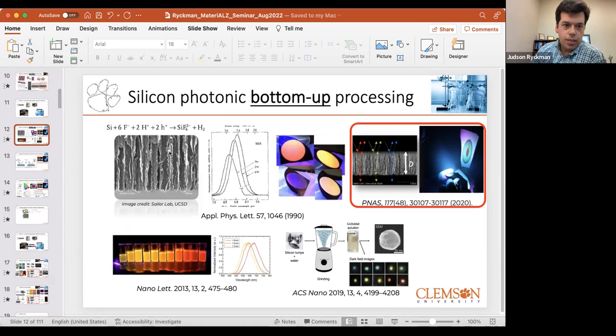My question is, how can I determine the number of pores and pore volume in a silicon porous film? Okay, yeah. So I guess there's a few different measurement techniques. You can do a standard SEM image, and then there's some distribution analysis you can do to see what is the average pore size. You can do cross-sectional imaging. There's also some more advanced techniques with gas adsorption analysis to get the average pore size and the specific surface area of the entire system. We also use gravimetry, where you actually measure the mass of the chip before and after porosifying it to see how much silicon you remove. So there's a few different techniques like that. I'll say in our case, the pores are disordered, so there's not a single tubular diameter. There's some disorder. So there's a mean pore diameter and some type of distribution around that.